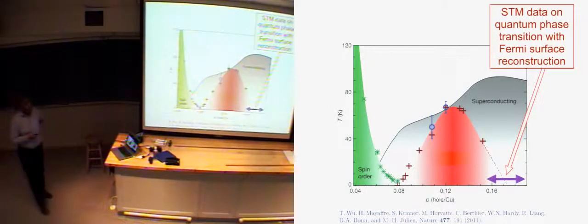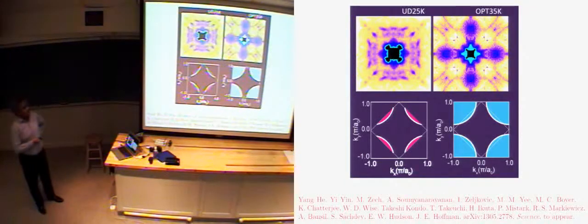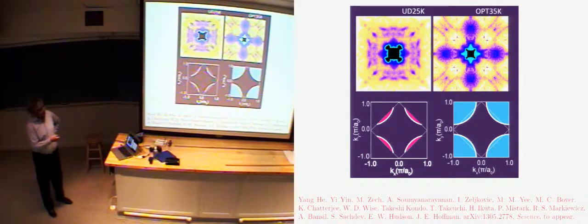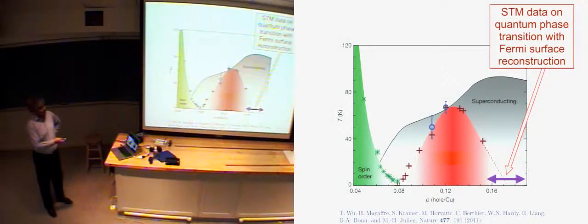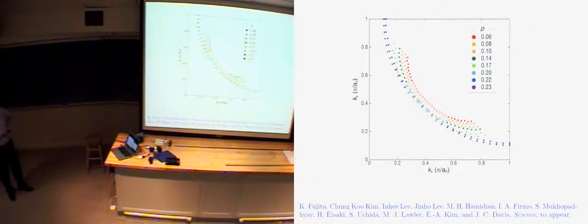We've done a more careful calculation where we put in this density wave order and actually computed the photoemission spectrum. You see these arc-like features and very faintly this pocket. One of the questions always was: if there's this pocket, why doesn't photoemission see it? The intensity is very weak. We took the same model, and Andrea Allais did a full calculation of the oscillation of the density of states by putting a magnetic field in physically and figuring out how the density oscillates. We take the Fourier transform of that, and in fact the area corresponds to precisely this small pocket you can barely see in photoemission. This is a full calculation — not a semi-classical argument of splitting orbits — of free electrons on a lattice in a magnetic field, and you see exactly the right period. At finite temperature, all of this other stuff disappears and you see this arc-like feature again.